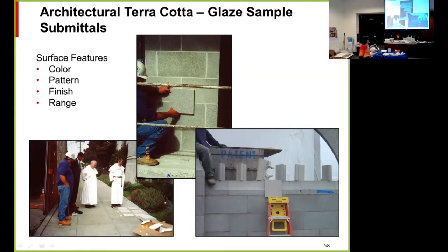The other thing is these older terracotta buildings, the kilns weren't as regulated as they are now. A lot of them were made in beehive kilns, so the terracotta was just all stacked up and fired, not the tunnel kilns, so the temperature had a lot more variation. So if you look at most older terracotta buildings, you'll see a lot of variation in color from block to block. But if you just pick one of those blocks and get a glaze match, the manufacturer is so much more precise now, it'll stick out like a sore thumb because all your new blocks are going to be one color. So we almost always require maybe 3 colors or 5 colors so that you can get that variation that you see on the original terracotta.